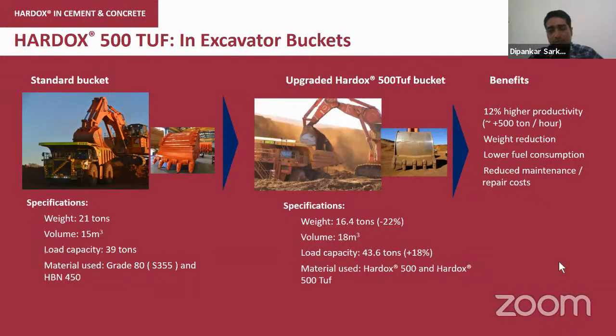So we went for the Hardox 500 tuff, which, since it has higher hardness and higher dent resistance than the Hardox 450 and the mild steel, of course, allowed us to decrease the thickness of some parts, which let us decrease the weight by 22%. From 21 tons, it became 16.4 tons. Also, decreasing the thicknesses and improving the design a little bit supported increasing the capacity or the volume from 15 cubic meters to 18 cubic meters. And the load capacity now increased from 39 tons to 43.6 tons, which means you gain 18% higher load capacity, you have better productivity. It was produced from Hardox 500 and 500 tuff.